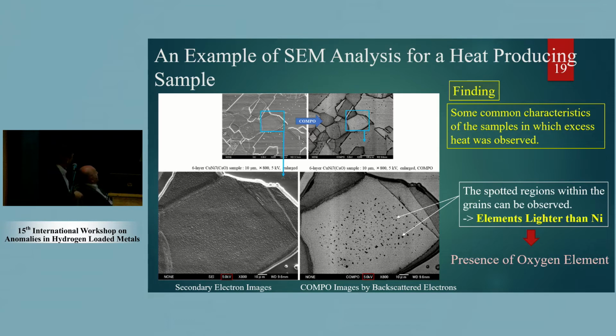And the next point is the results of SEM analysis. This is SEM analysis for a heat-producing sample. We found some common characteristics of the samples in which excess heat was observed. We observed this kind of spotted region within the grains. This is a COMPO image by backscattered electrons. We can see the spotted region. Maybe this means elements lighter than nickel; mainly we have nickel. After that, there is the presence of the oxygen element. Okay, I will show you the detail.